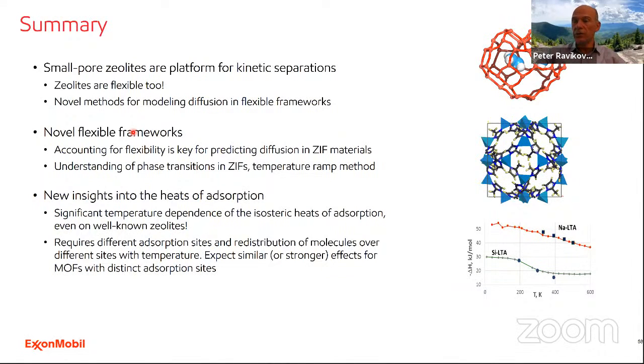And the problem is to predict the occurrence of these transitions and at what conditions they occur, and how you go from an X-ray structure reported for a particular MOF at particular conditions to a more general understanding of the behavior of the material in a range of temperatures and adsorbed molecules. The last topic which I covered was the heats of adsorption. We were quite surprised to demonstrate that there is actually a significant temperature dependence of the heats of adsorption, even for well-known zeolites. We expect that this temperature dependence will be more prominent for materials where we have more distinct adsorption sites, for example, MOFs. And so the caution is that if you use the Clapeyron-Clausius equation, you should use it in as narrow a range of temperatures as possible to be able to do accurate calculations of the heat of adsorption.